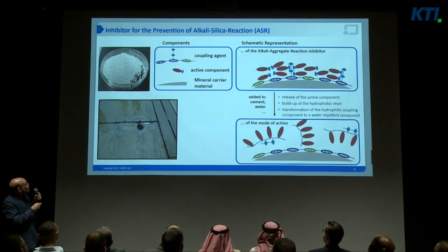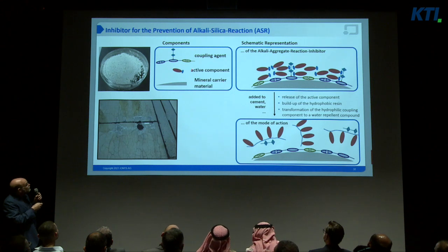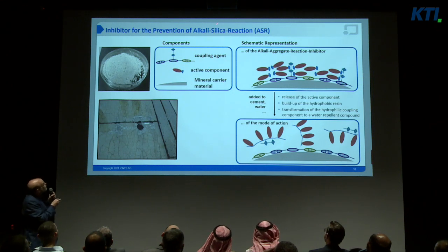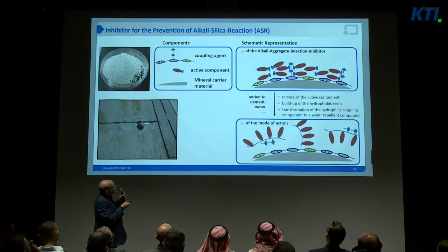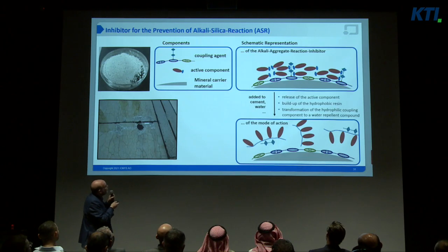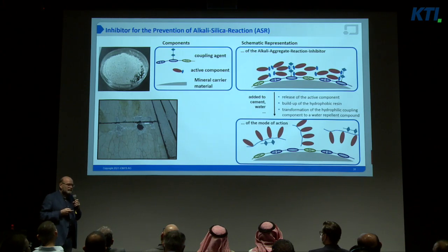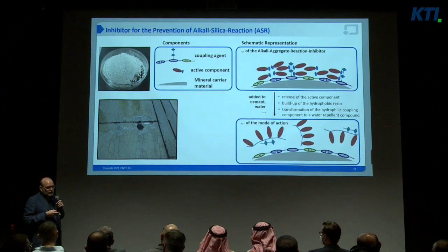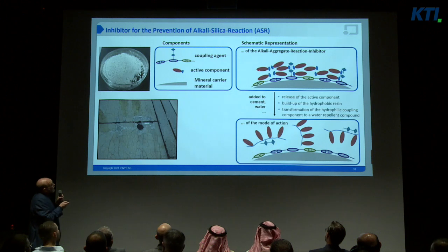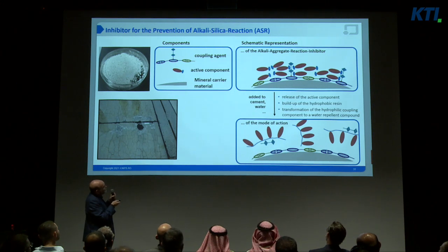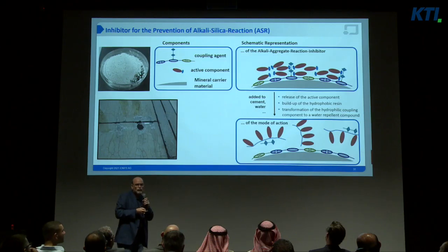This powder is a complex combination of a mineral carrier material, an active component which prevents the ASR reaction, and a coupling agent. In this way, we put the active agent on the surface of this mineral powder, and then we add this powder to dry mix systems, for example cement or other cement-based dry mixes. Then we add water, and in a determined process these substances are liberated, and the mineral substance will work like microsilica, because it's a type of microsilica. So we have two actions: the action of the microsilica and the prevention of the ASR reaction.